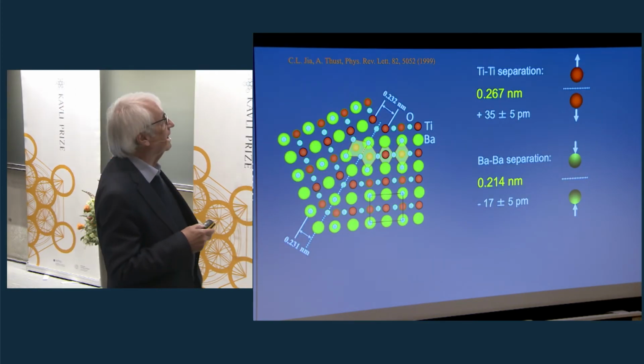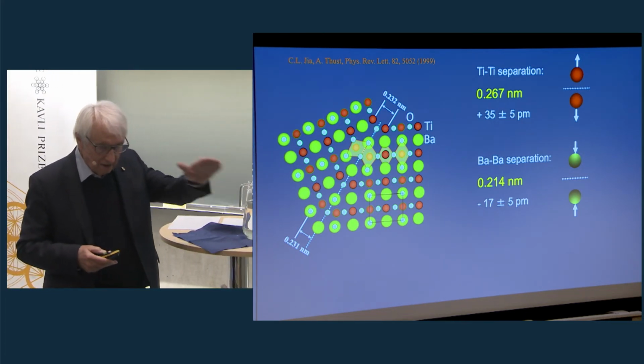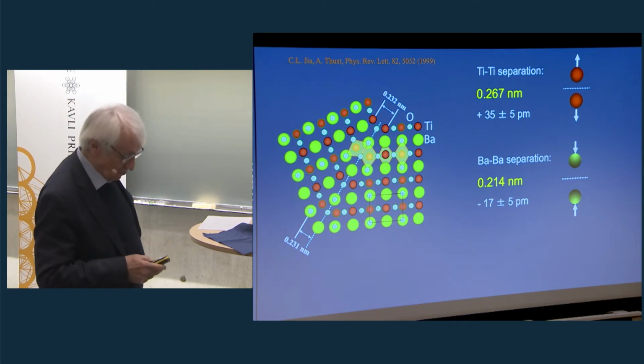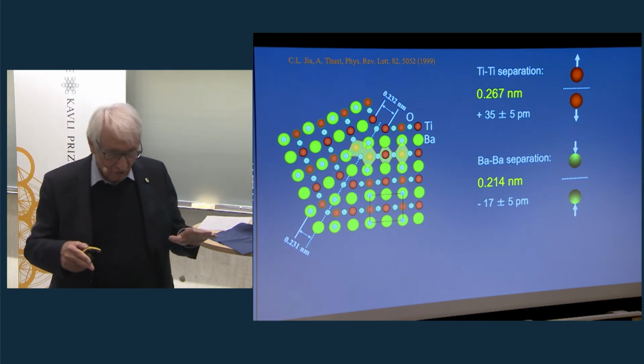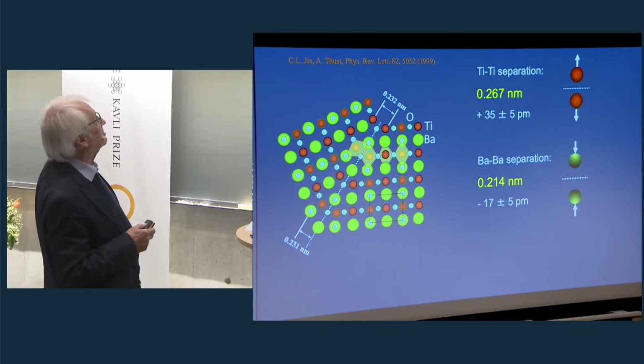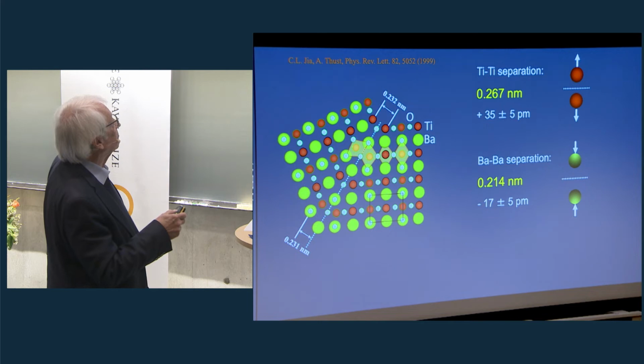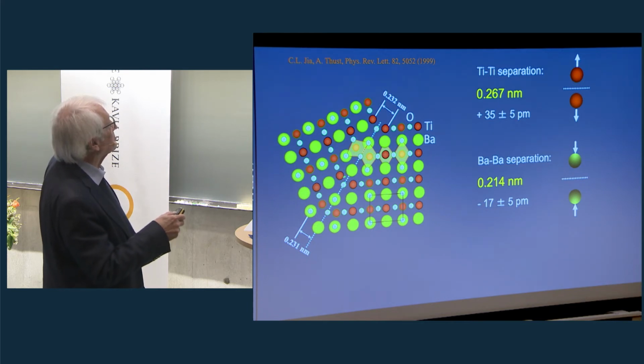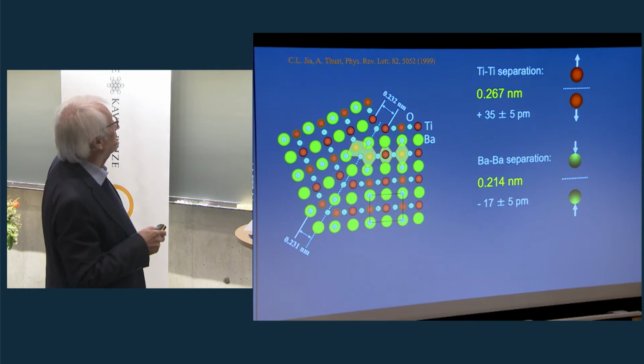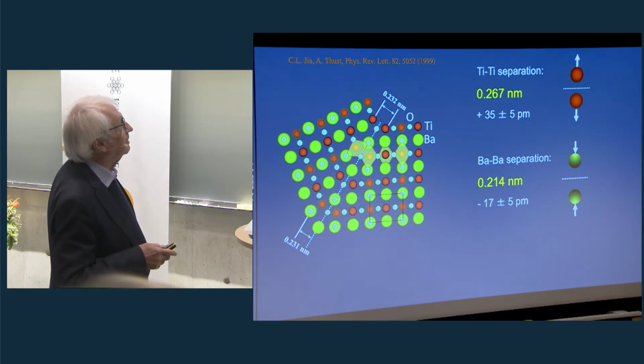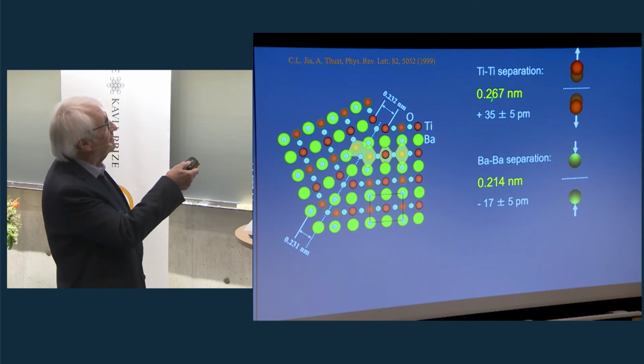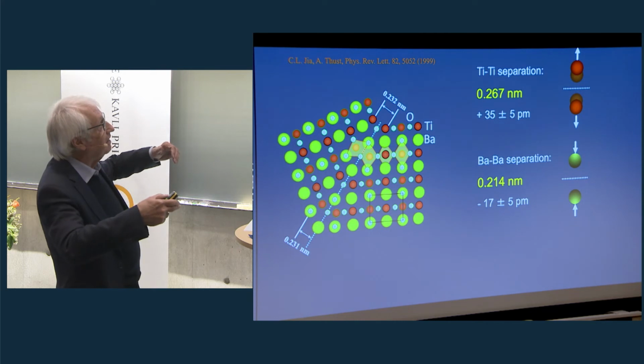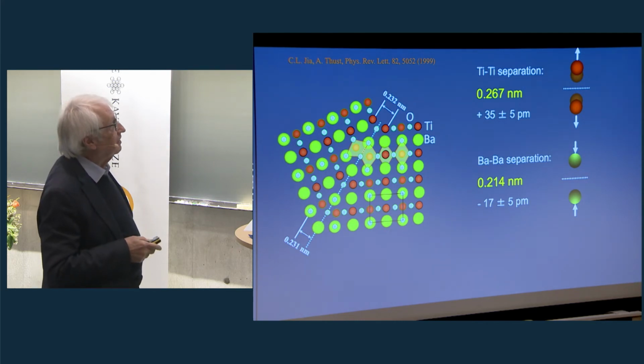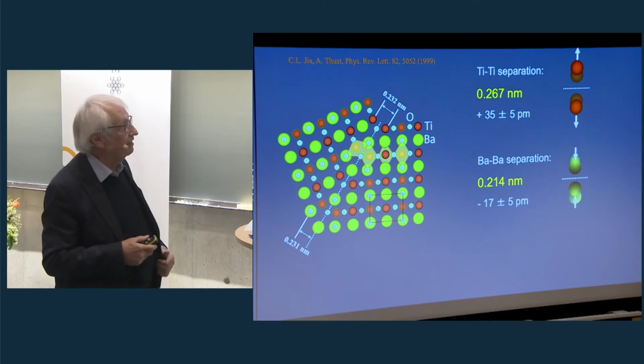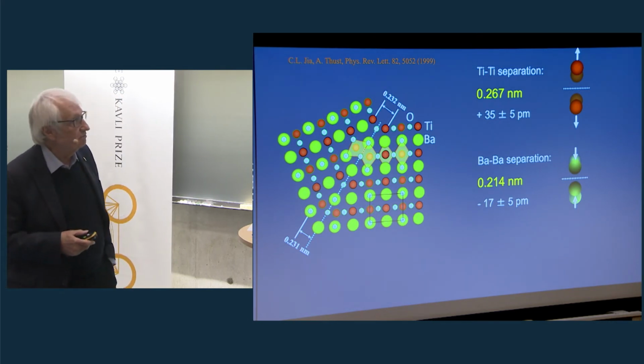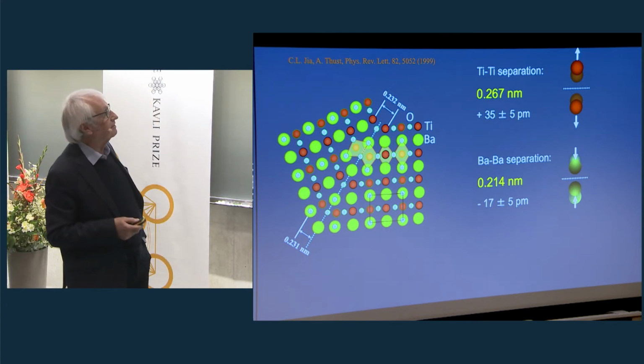We also measured the atomic distances in these twin boundaries, because this was also for a long time a matter of controversy. And so we did measurements of this, this is the twin boundary, and now we measured the distances, for instance, for these two titanium atoms, or the green ones in this case are barium. So we find that the titanium atoms are shifting apart by 35 picometers. The barium atoms are moved together by 17 picometers. Wonderfully small numbers. So I really like these small numbers.